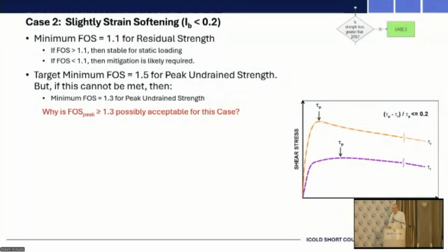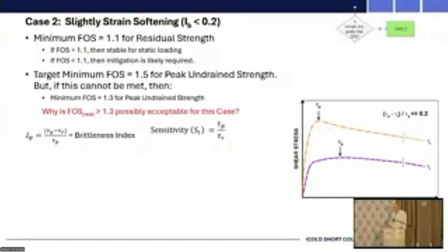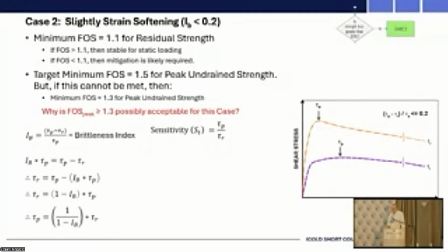But you ask the question, so why is a factor of safety of 1.3 acceptable for this case? It's not irrational, it's not arbitrary, it didn't come out of thin air. It's based on the observed behaviors that are represented by the stress strain curve. And so I'm going to just walk through a little bit of a derivation here as to how we got to that logical conclusion. So if you'll think back to the brittleness index, which is the peak strength minus the residual strength divided by the peak strength.